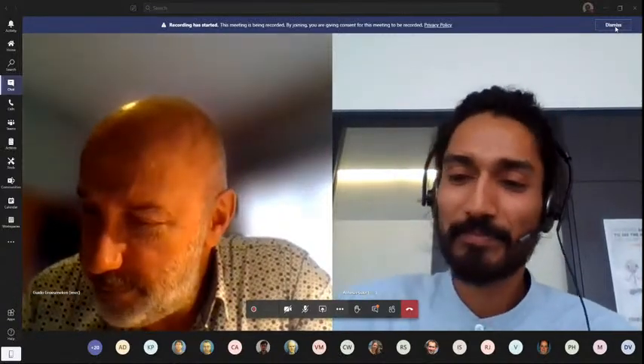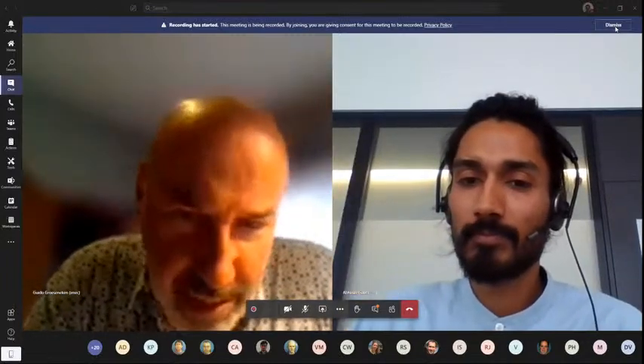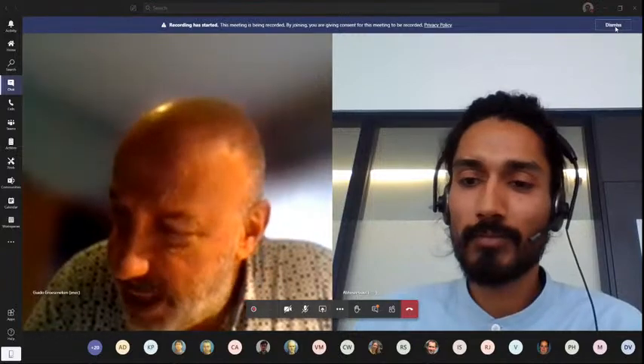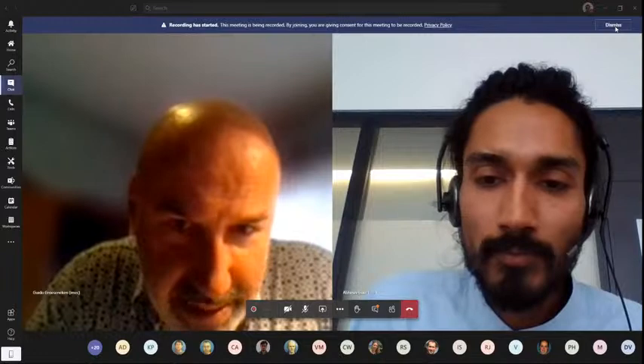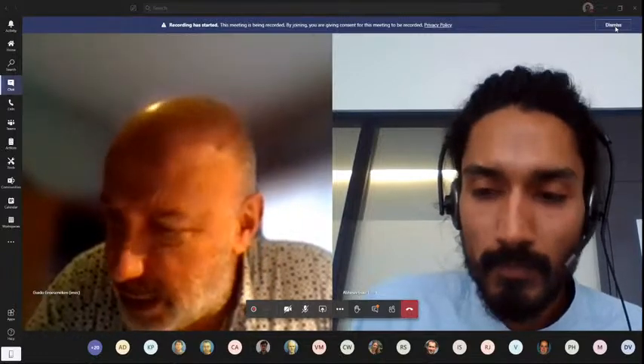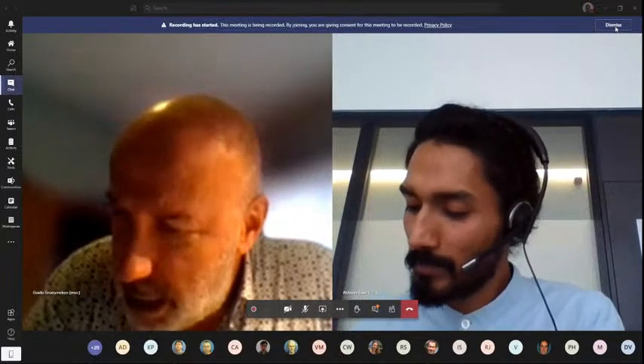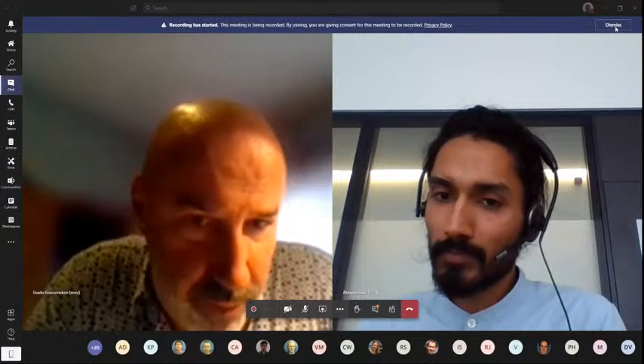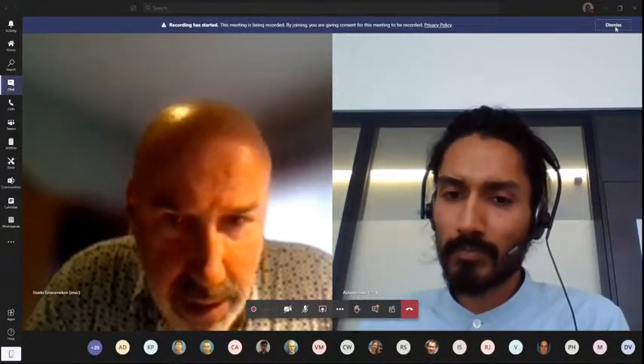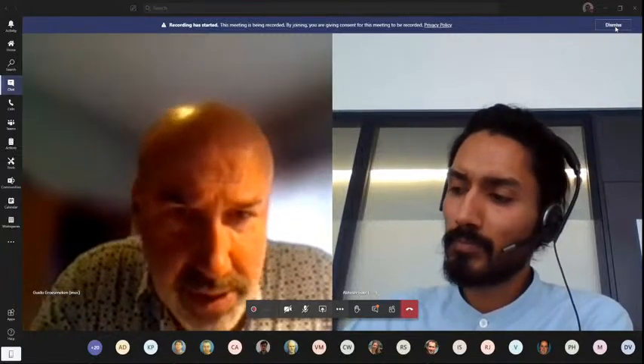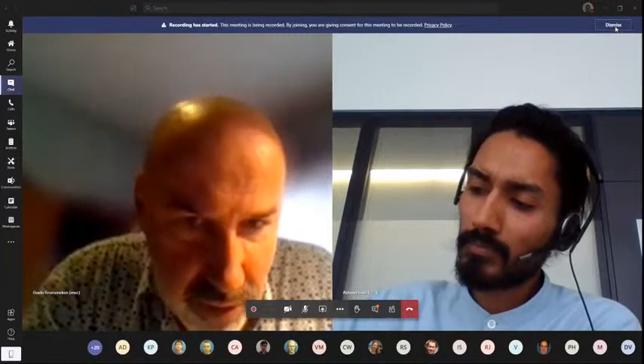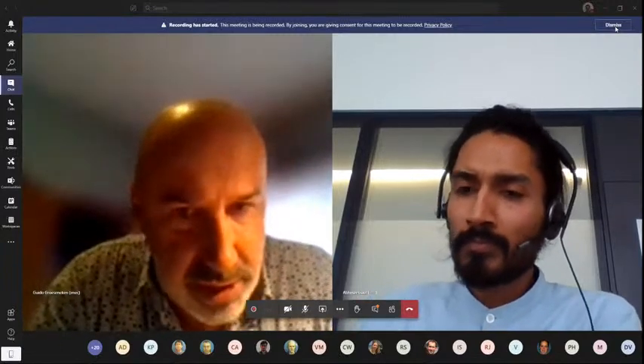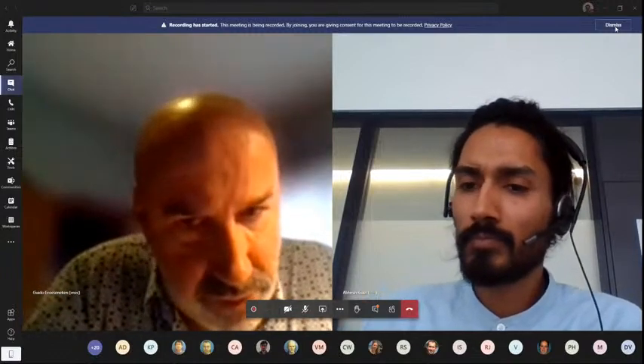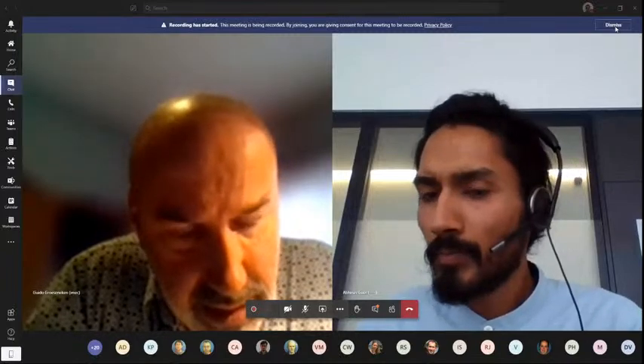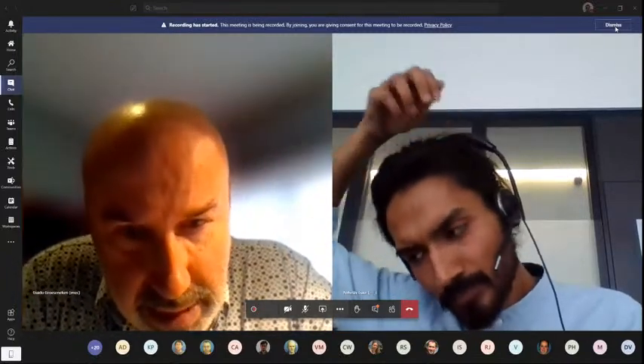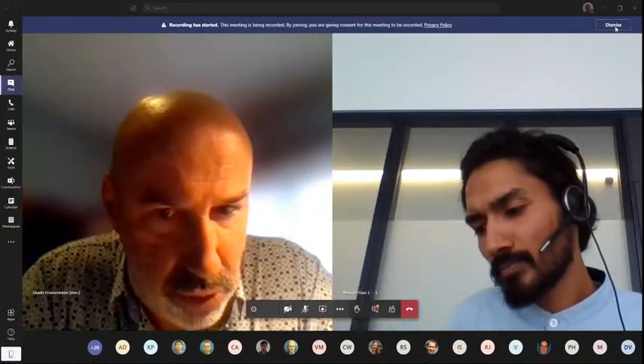Okay, good. Then another question is about the comparison between hafnium oxide and STO dielectrics. There you find that the STO gave you much better mobilities than the hafnium oxide, I think in chapter 5 as well. Still, you did most of your work on hafnium oxide, right? Most of your samples are done in hafnium oxide. Would you recommend STO as a dielectric, or is this again just maybe a coincidence or a statistical variation, the fact that you have better results for STO than for hafnium oxide? Or is this a fundamental difference? And would that lead us to conclusions concerning which dielectric to use?